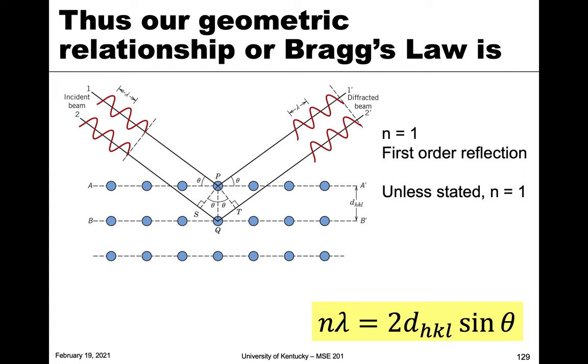When we're applying Bragg's law here, we're going to look at what's called first-order reflection, and that's when n equals 1. When we apply this, we're always going to have n equal 1. But just keep in mind that it can really be any integer. It can shift over 1 wavelength, or 2 wavelengths, or 3, and still be in phase in accordance with constructive interference.